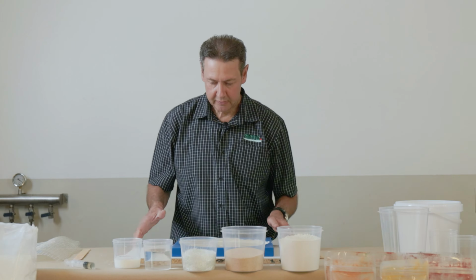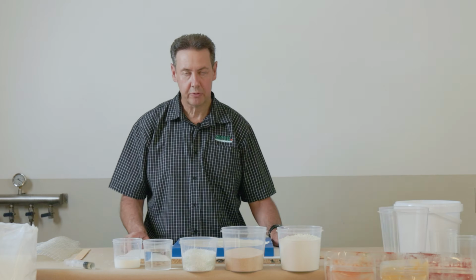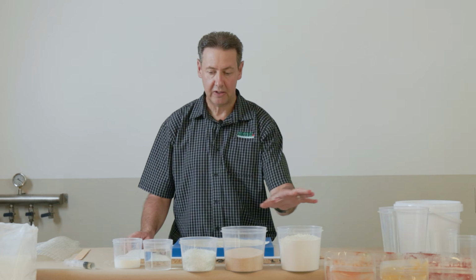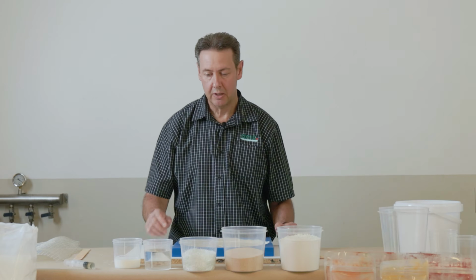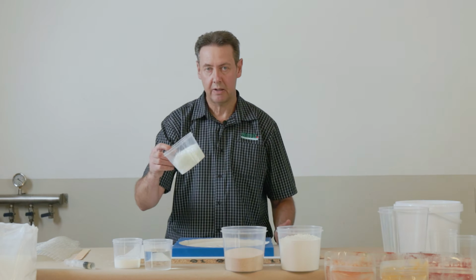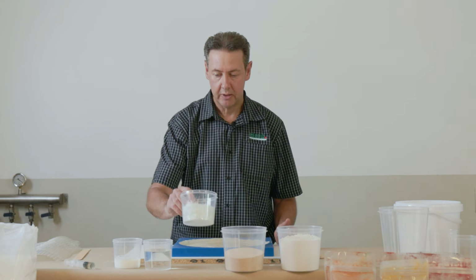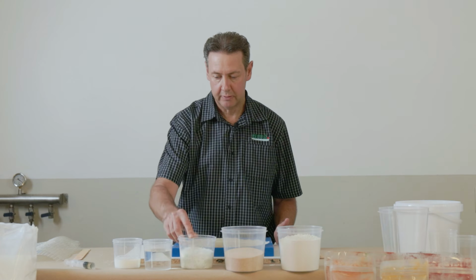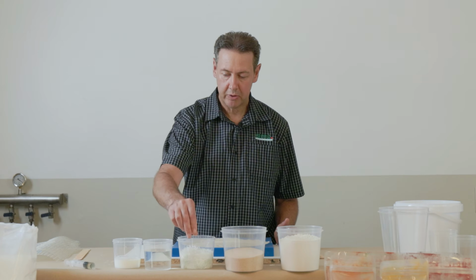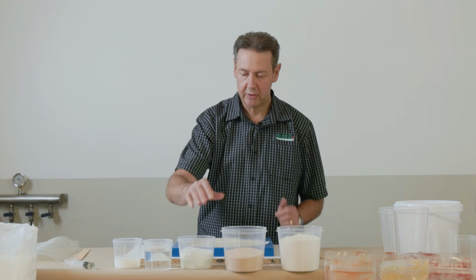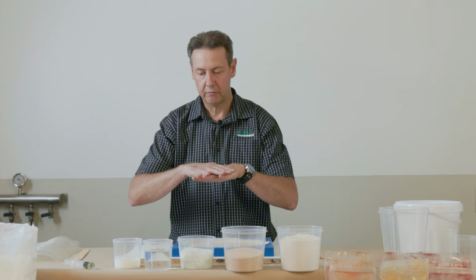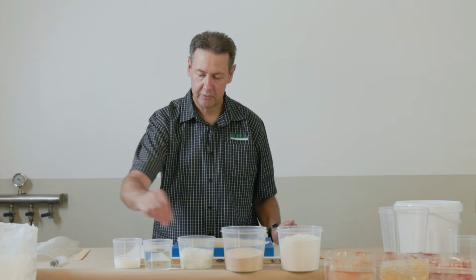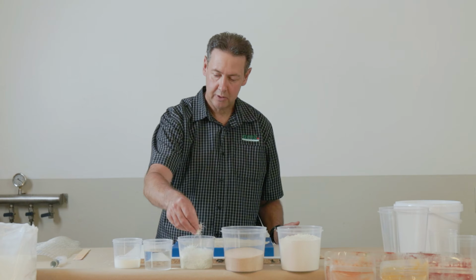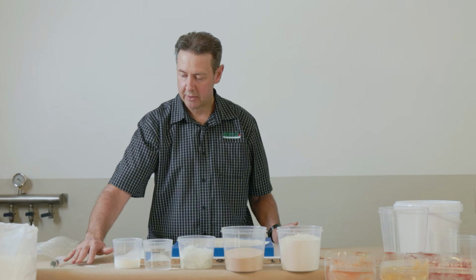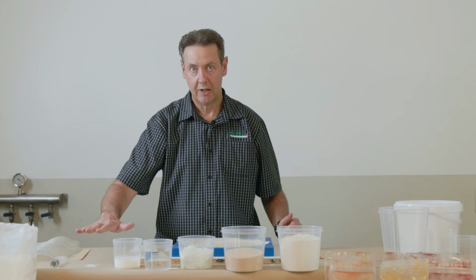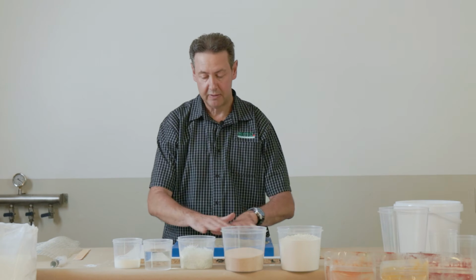So this next step, as I mentioned, is going to be the reinforcement section, and this is where we're going to use exactly the same mix as we did for the first coat, but we're going to incorporate the alkaline resistant glass fibers. So we've got our 18 mil fibers, and what's quite important is that we want these fibers to be as flat as possible for the ultimate strength. So if we put some of these fibers down on the surface like this, that's the orientation with these fibers being flat that we want to have in this mix.